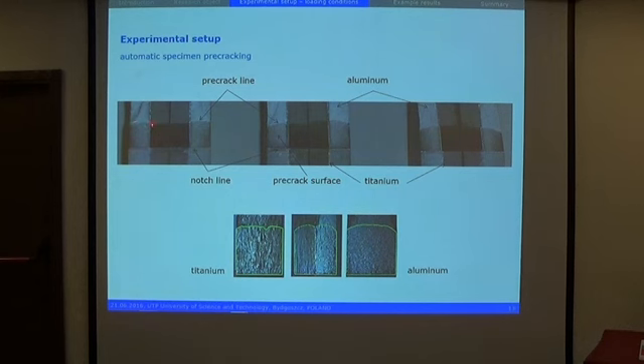For example, here we have the crack line in the aluminum alloy. The crack length is bigger than in titanium. Here it's almost the same, and here is quite another situation. Analysis of the pre-crack surface of titanium, aluminum, and layered material shows that the preparation of a proper crack line in the compact tension specimen is very, very hard and difficult, and the only answer is to produce a lot of specimens and check only the good specimens after the test.